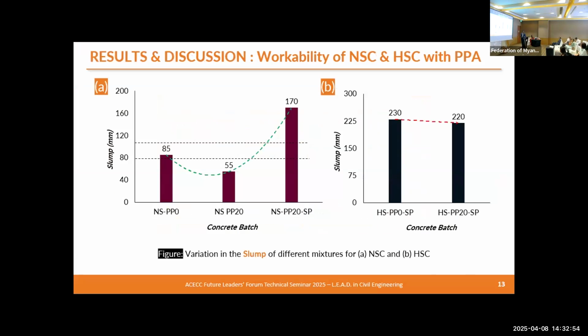Going deeper into the different strength parameters, this explains the workability. You can see that there's a reduction in workability with the incorporation of plastic waste in the concrete, similar to the normal strength concrete. In high strength concrete also we can see that a reduction is there, but for the normal strength concrete this reduction is prominent because we haven't included the superplasticizer yet, but here the superplasticizer is there, so the reduction is negligible.